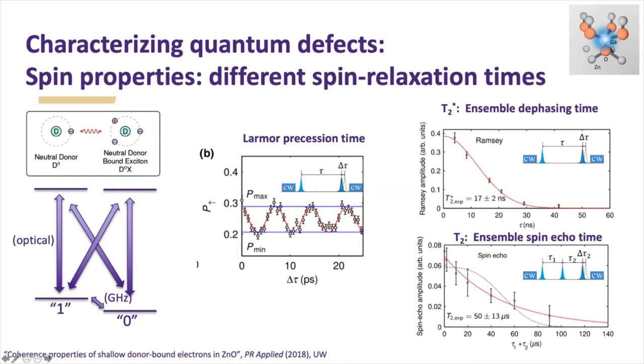And what you can see is that this qubit precesses at a rate or a time scale of about 10 picoseconds. So very, very quick. And so our way to measure something so quickly, we can't just use microwaves. We actually have to use fast laser pulses in order to detect this very fast precession. Then we can also look at how quickly this superposition state decays. So that is done by measuring the amplitude of this as a function of time. And here you can see that it decays now in 17 nanoseconds. So that's not super long, but we're already 1,000 times longer than that precession time.